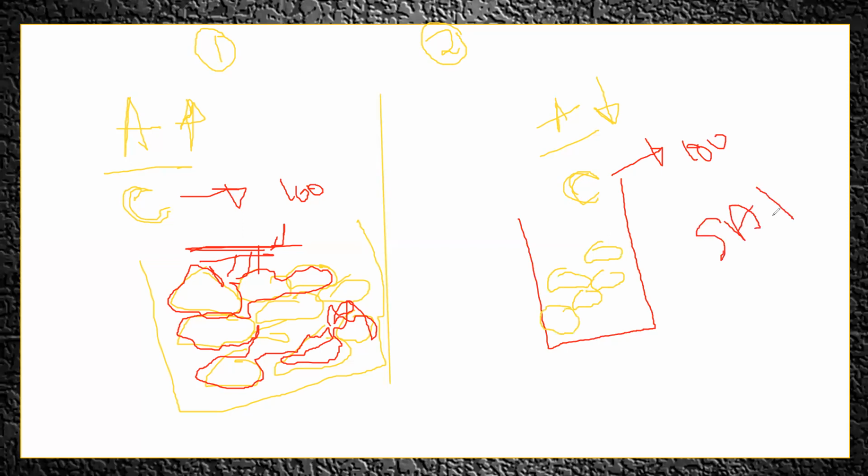Surface area is going to come down. If surface area is going to come down, the cement paste required will also be less to cover the surface area of this. If less cement paste has gone in covering the surface area, then what will happen? More cement paste is remaining for me. If more cement paste is remaining, then what is going to happen? There will be very good lubrication. That means the workability is going to increase, right? Because in both cases, the cement paste remains the same.